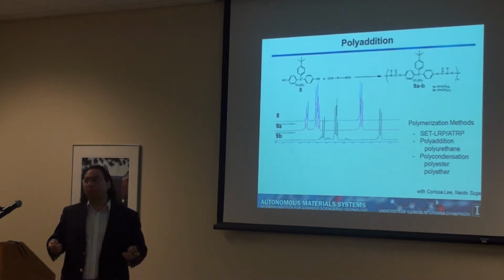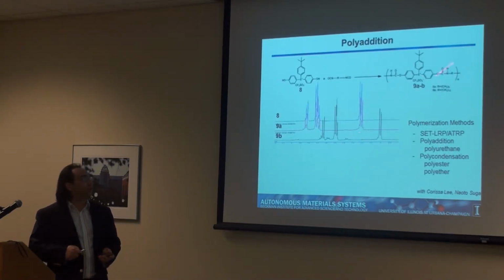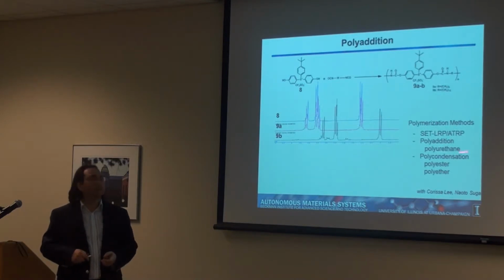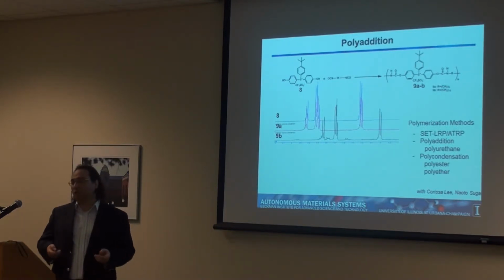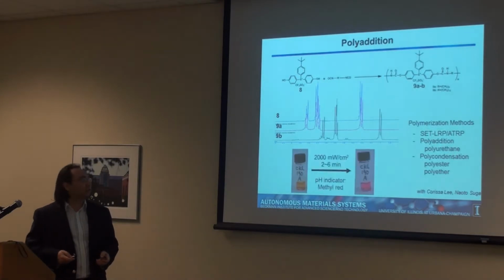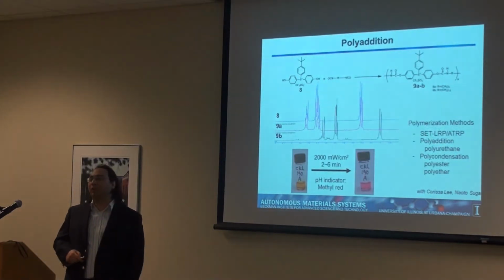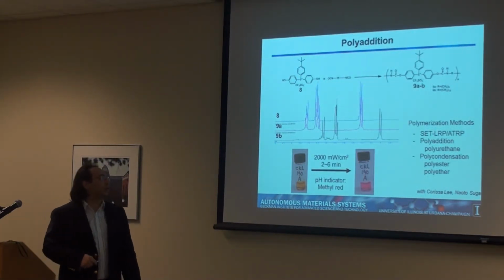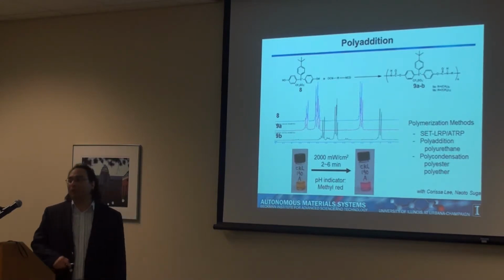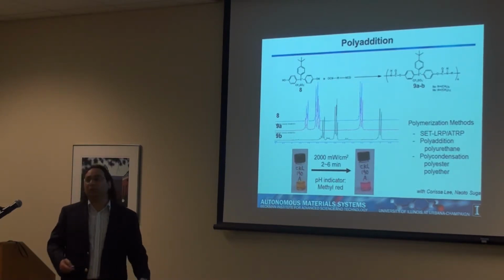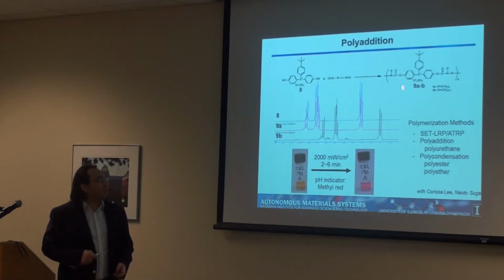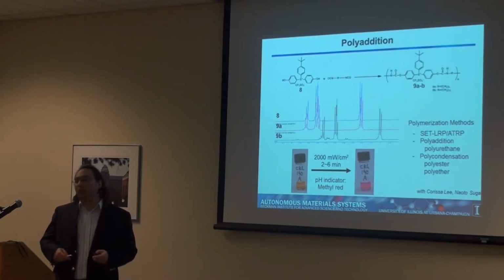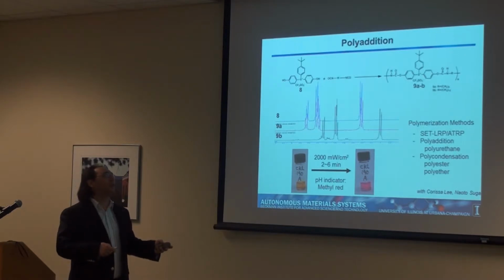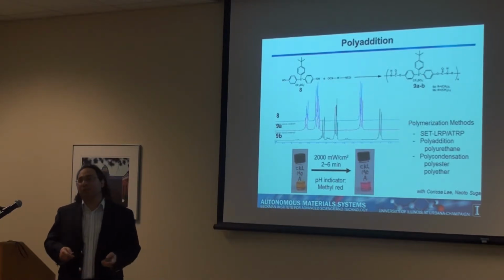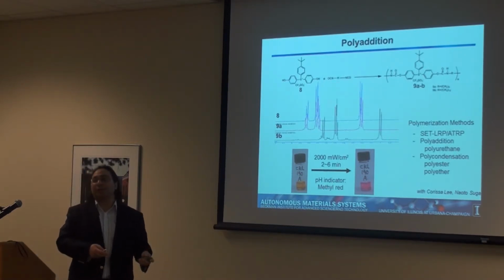By the way, the polymerization by polyaddition works quite well. So we were able to make polyurethanes, for example, and in this case, the NMR showed that the structure keeps constant. And it's still a photoacid generator, so it's very nice that you can just shine UV light in the presence of a pH indicator and see that the structure is still there and still works. But if you look at this structure, this is not a common polyurethane. This is a polyurethane that has a lot of this specific monomer that I use, and that's not the kind of material that I want to do.